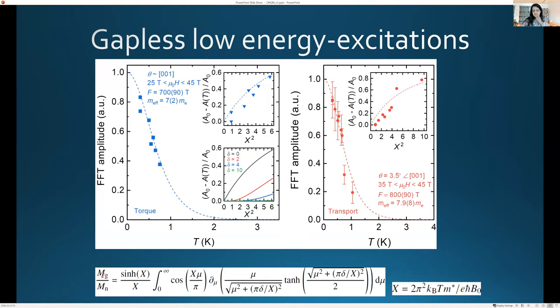So this is the ratio of quantum oscillations in a gap state, which is mg, so the size of oscillations in a gap state compared to the normal state. So if there was no gap, then this would drop out completely and just get conventional sinh x by h, x behavior for the normal quantum oscillations, which probably you might be familiar with, which shows why quantum oscillations grow as the temperature reduces. This is just the Lifshitz-Kosevich form.